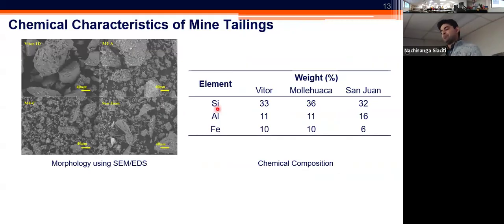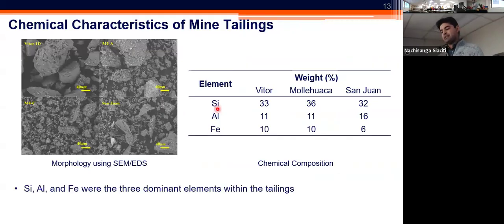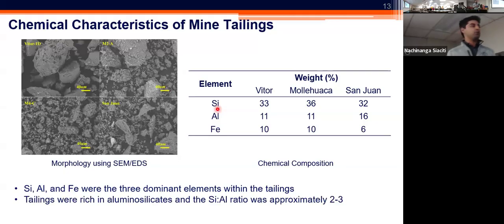So some of the takeaways so far in terms of the evaluation has been that silicon, aluminum, and iron are the 3 dominant types of elements within these tailing materials. And often you have some favorable ratio of the silicon to aluminum. In fact, in these tailing samples that we had a chance to work with, the tailings were rich in aluminum silicates, and the silicon to aluminum ratio was ranging from 2 to 3. That often is a good predictor of the performance for geopolymerization and the success of the geopolymerization. But that doesn't necessarily mean that we always will be lucky in terms of having a good ratio of the silicon to aluminum on the tailings as collected and in their raw form.